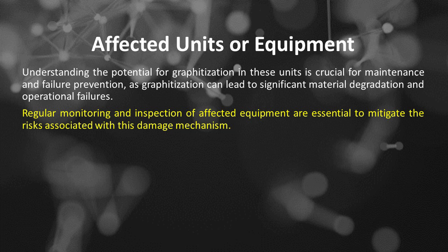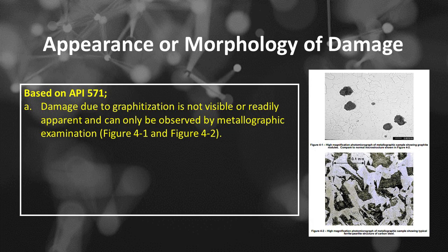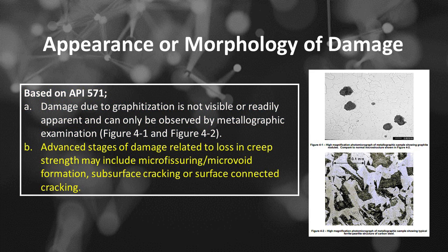Regular monitoring and inspection of affected equipment are essential to mitigate the risks associated with this damage mechanism. Appearance or morphology of damage. Based on API 571, the first is, damage due to graphitization is not visible or readily apparent and can only be observed by metallographic examination, see Figure 4.1 and Figure 4.2. And the second is, advanced stages of damage related to loss in creep strength may include microfissuring/microvoid formation, subsurface cracking or surface-connected cracking.